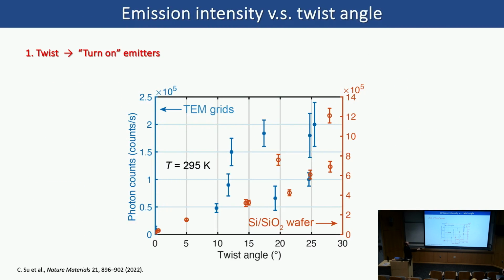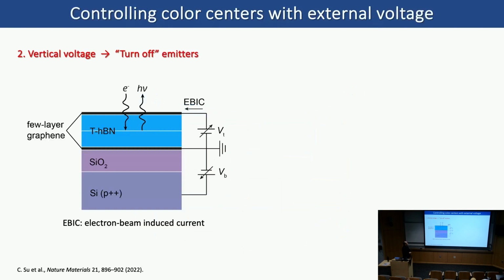Okay, and we did some correlation between photon counts, how bright it becomes, with twist angle. So from 0, you could see there's almost no photon that's actually being enhanced. But once you give it a twist all the way up to 30, there's a huge boost in terms of its defect emission. There's almost like 50 to 100-fold of brightness change here. So that was a way you could turn some emitters from off state to on state by just giving it a twist. It turns out that we also figured out a way to make those twisted bright emitters become dark again.